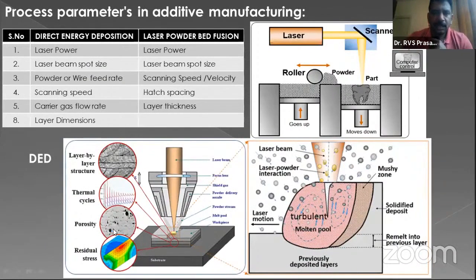So now, as per my agenda of the talk, I will go into more detail on direct energy deposition. If you consider process parameters in additive manufacturing, there are direct energy deposition versus laser powder bed fusion. In direct energy deposition, these are laser power, laser beam spot size, powder or wire feed rate, scanning speed, carrier gas flow rate, and layer dimensions. So these are very important.